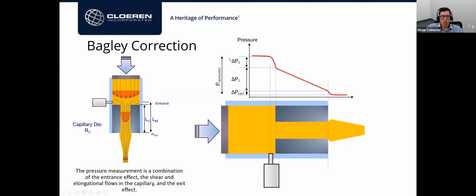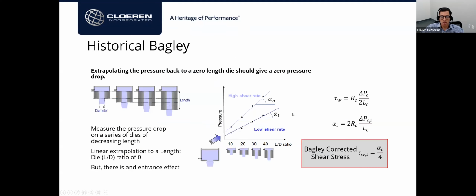So the Bagley correction consists in trying to determine this entrance pressure by changing the L over D ratio of the die. So that's the historic Rabinowitsch correction. I'm sorry, Bagley correction. And so basically you would plot the pressure measurement as a function of different L over D ratios. So you would have to use 3-4 different dies, repeat the measurements, and collect pressure as a function of this L over D for different shear rates. In the end, at the intercept here, you can calculate the entrance pressure, or with the slope here, you can directly calculate the corrected value of shear stress.